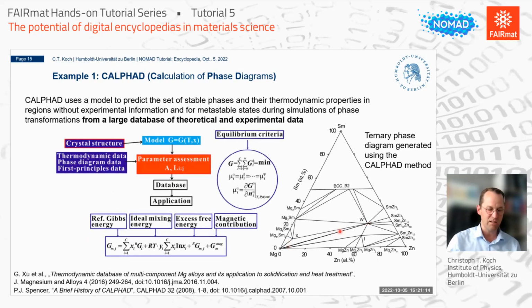So by minimizing the Gibbs free energy of the system, assuming that the system really obeys this equation, where the Gibbs free energy is basically a sum of different energy terms that are scaled with coefficients, and these coefficients are fitted to the known data points that you have. And these known data points can come from materials databases containing experimental data, but to some degree they're also augmented by entries that are calculated. So you have these different contributions, and they each scale with a parameter that is fitted. But this actually works quite well.